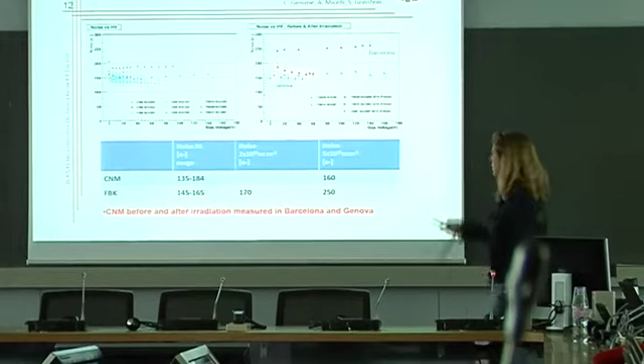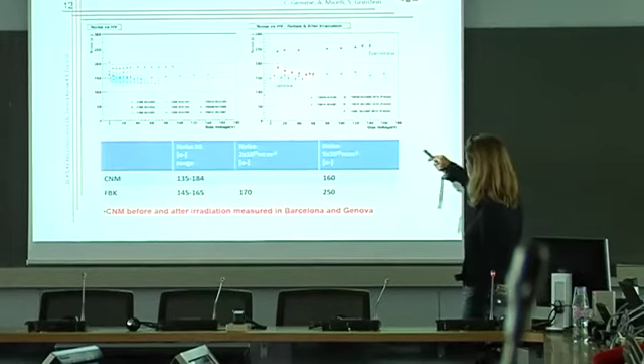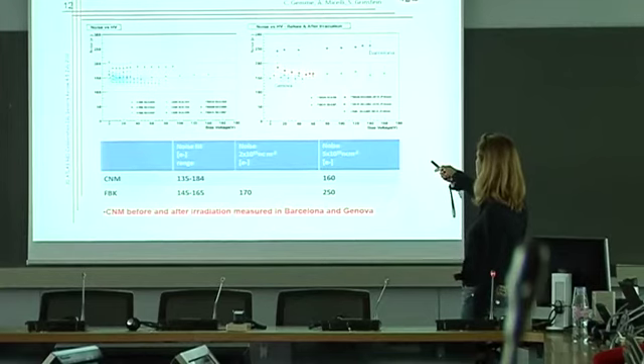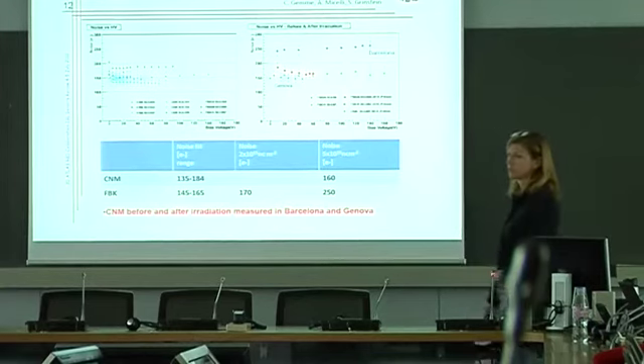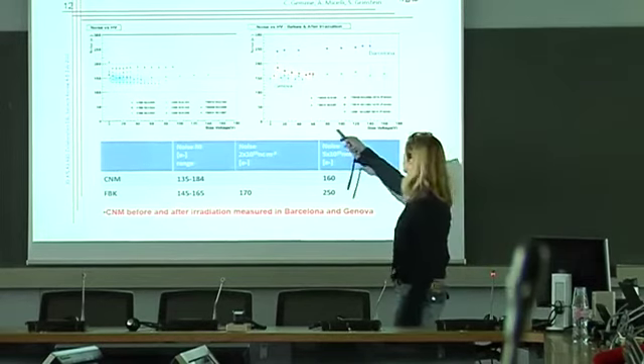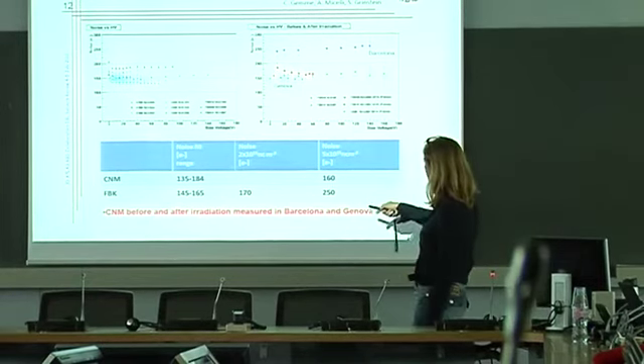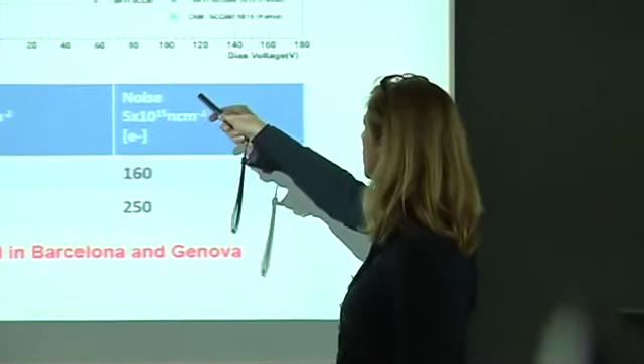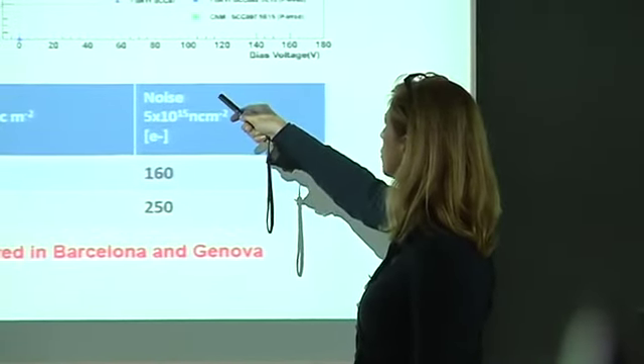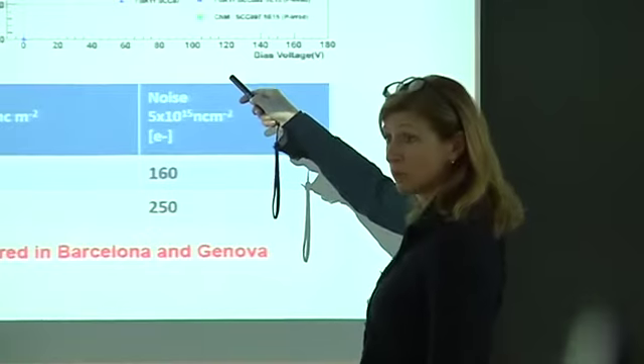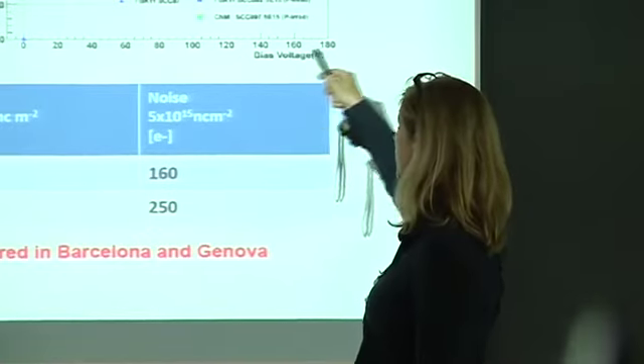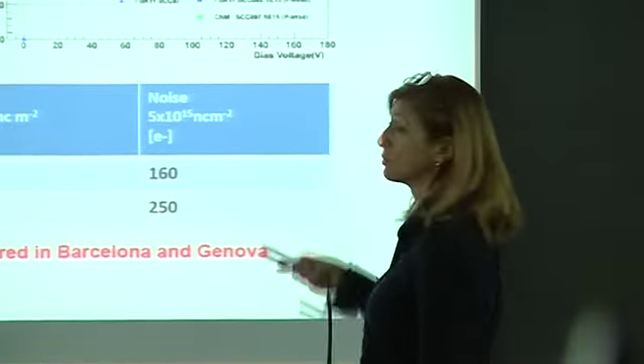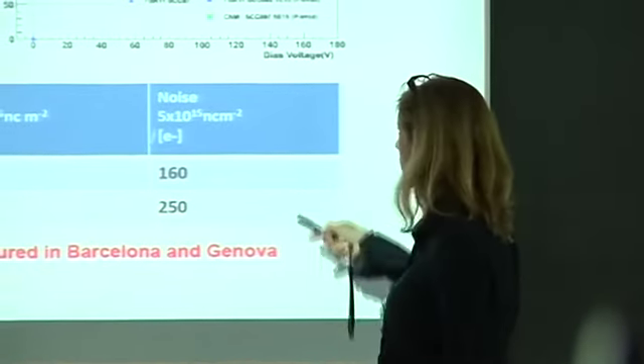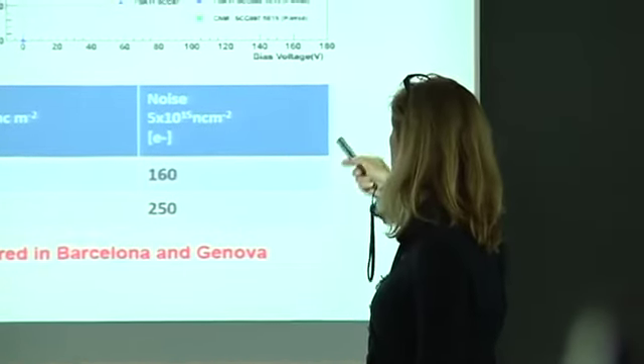What's the upper blue line? The upper blue line, yes. That's the other FBK. The blue one is an FBK 5 times 10 to the 15. Okay, so I'm not mistaken with the number you quote. No, I'm quoting the number, so it's perfectly correct. We're going from here with the blue, which is non-irradiated, to the same device after irradiation. And this is the difference between the two. That's neutron irradiation. This is also irradiated with both of them 5 times 10 to the 15.